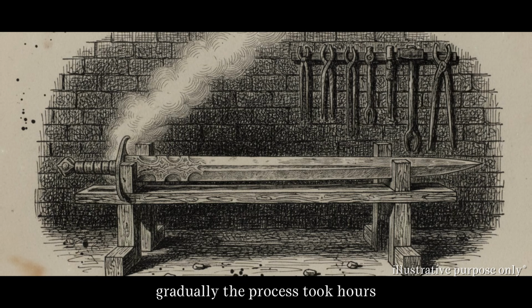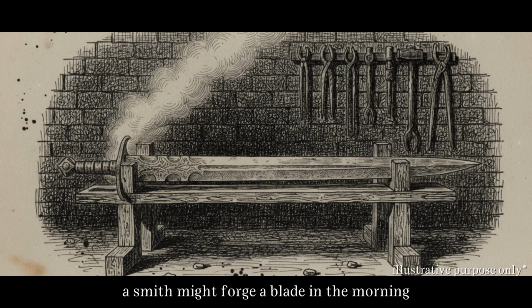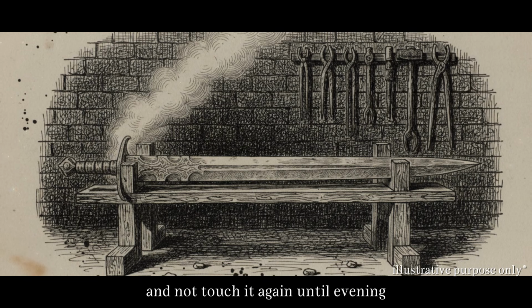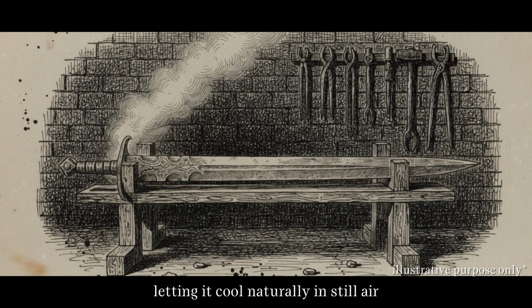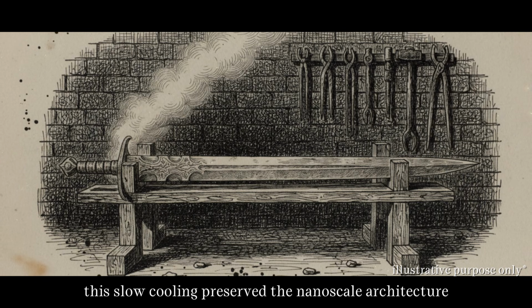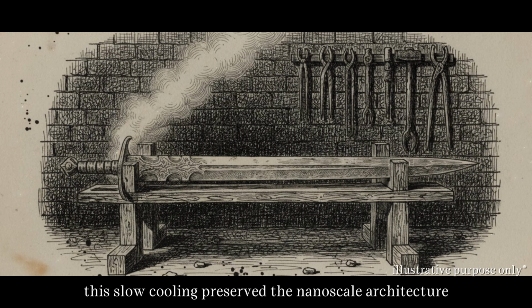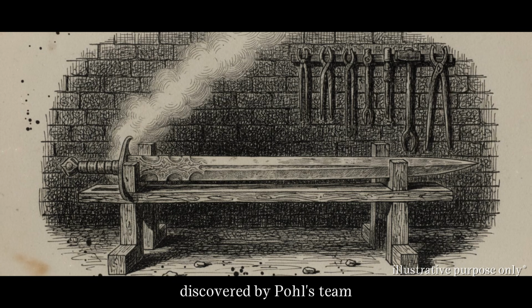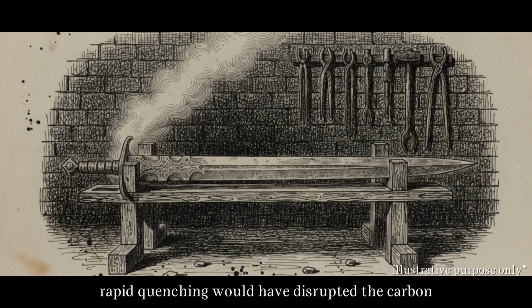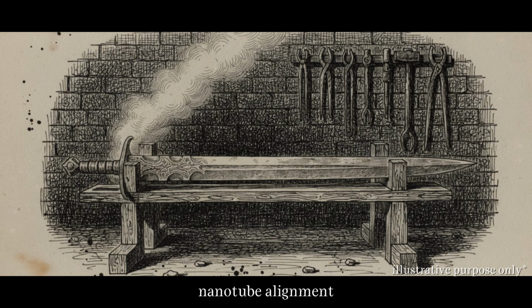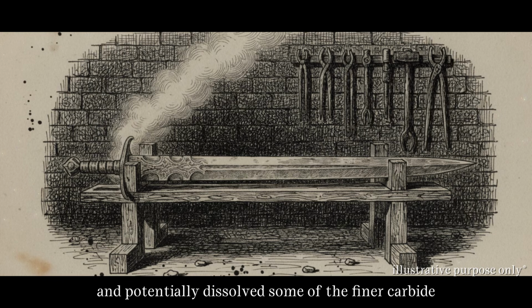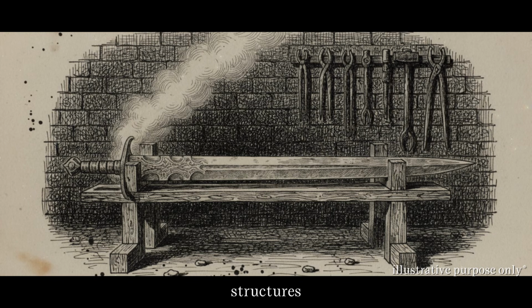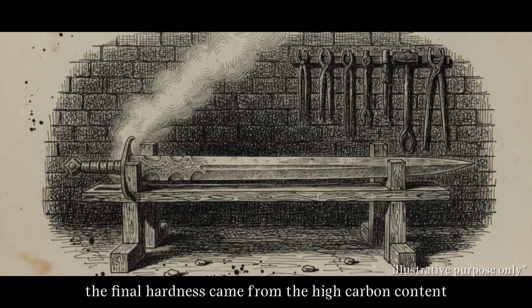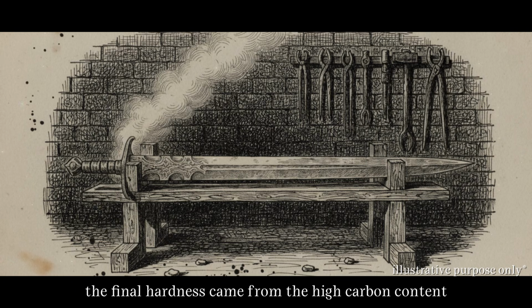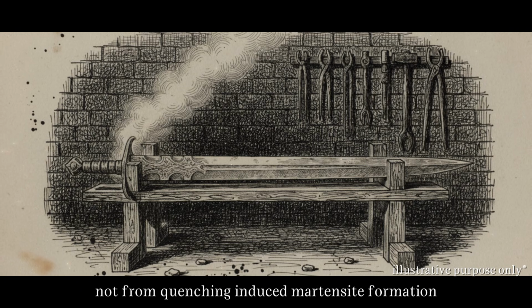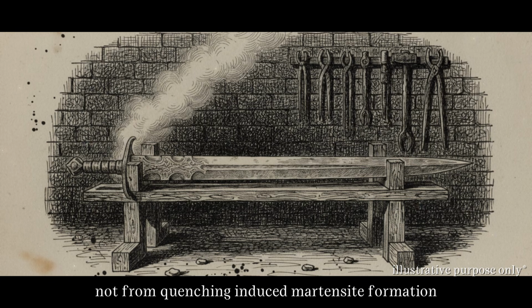The process took hours. A smith might forge a blade in the morning and not touch it again until evening, letting it cool naturally in still air. This slow cooling preserved the nanoscale architecture discovered by Paufler's team. Rapid quenching would have disrupted the carbon nanotube alignment and potentially dissolved some of the finer carbide structures. The final hardness came from the high carbon content and the carbide networks, not from quenching-induced martensite formation.